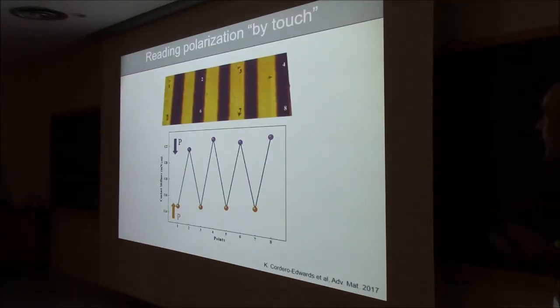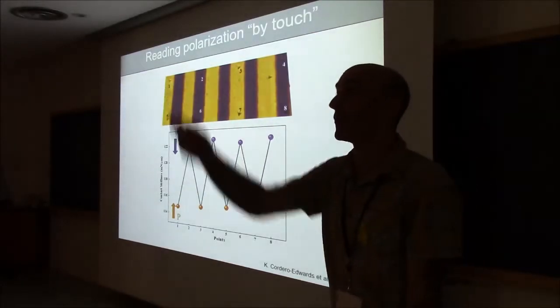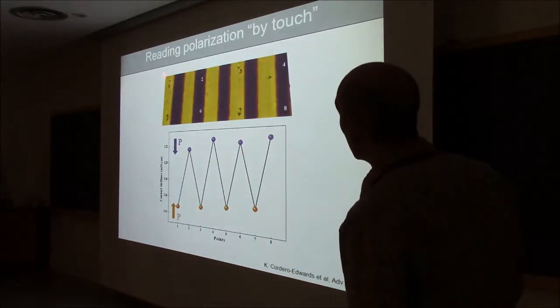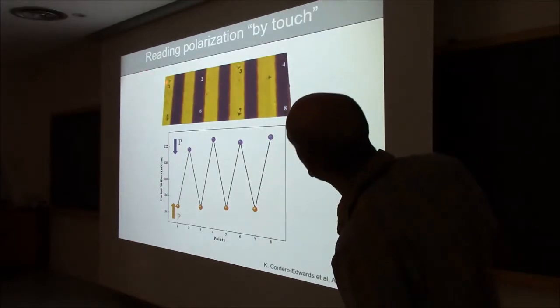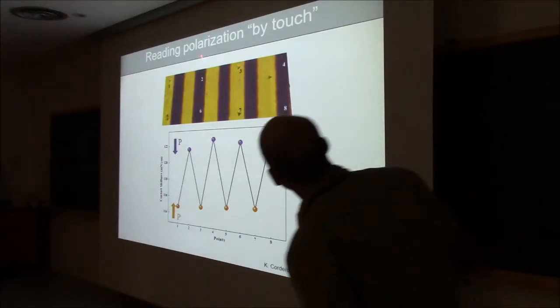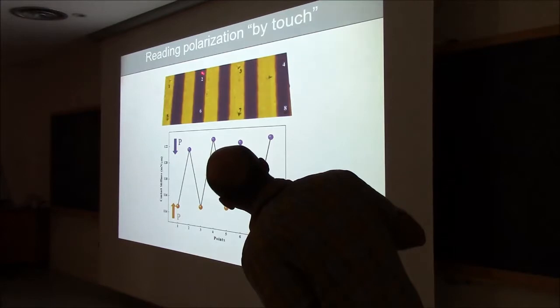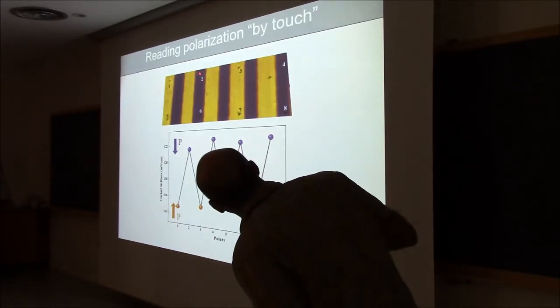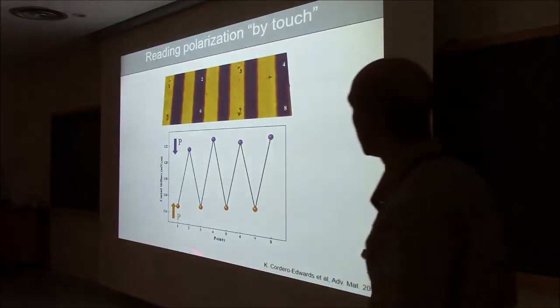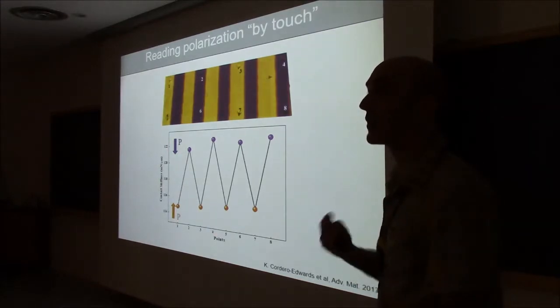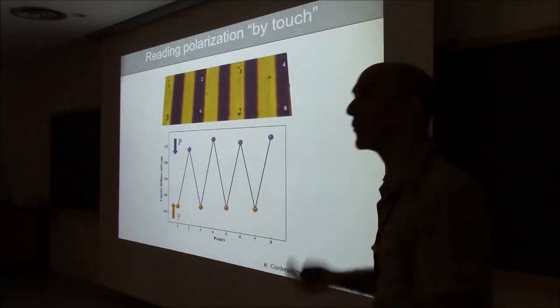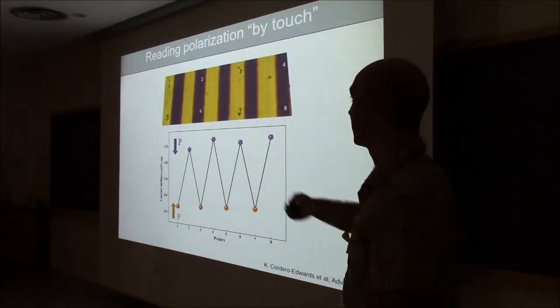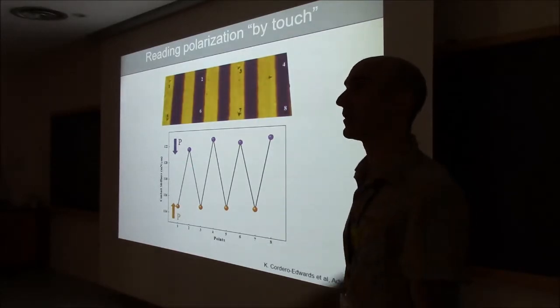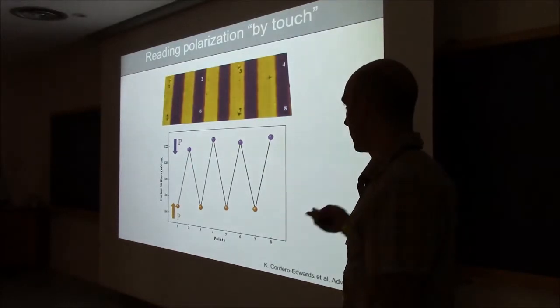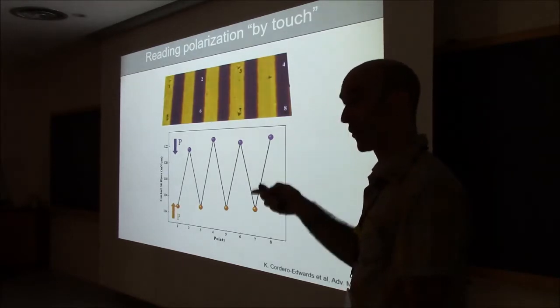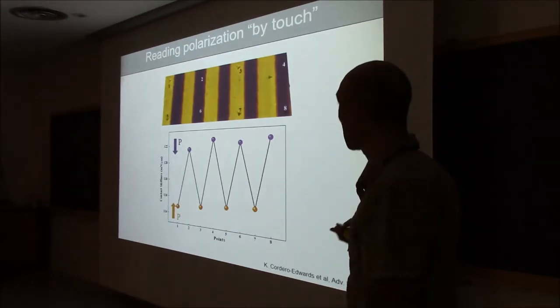We will not go into the details. So if you take a periodically poled lithium niobate crystal and you indent on the up polarized domains, or you indent on the down polarized domains, maybe you cannot see them, but trust me, there's a hole here done by the indenter. You see that the contact stiffness is different, right? It's pretty cool. It means that we've read the polar state of our domains by punching a hole. This is the very definition of destructive readout because we are punching holes.